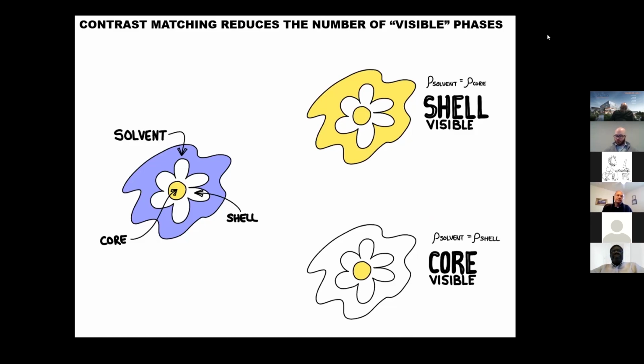We can chemically treat our systems. Let's say it's a hydrogenous system, so there's lots of hydrogen in it. We can chemically treat the system and exchange some of the hydrogens on certain parts of the sample so that we can contrast match out features that we don't care to see. So in the upper right-hand corner, I can make that shell visible by matching what's called the scattering length density of the solvent to that of the core, or just basically deuterate the solvent and make it identical to what's in the core. And that makes the shell visible. We can make the core visible by making the solvent and the shell identical. And so then that makes the core pop out.